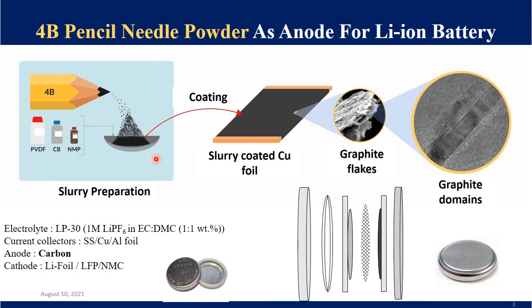In this work, a 4B pencil needle powder based conventional slurry coated anode with a binder and conductive additives is prepared and tested as anode in a coin cell setup. The pencil lead powder mainly consists of a nanocomposite of graphite and clay, as different grades of pencil vary in their composition. We have chosen 4B pencil lead powder, which has a high graphitic content of 79% and a moderate clay percent of 15%.